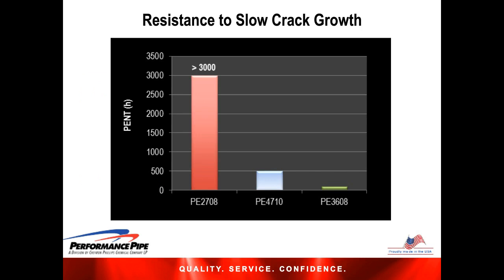For resistance to slow crack growth, a PE 4710 material requires greater than 500 hours of PENT testing, compared to the previous PE 3608 material requiring only 100 hours of PENT testing, while the new PE 2708 material achieves greater than 3,000 hours of PENT testing. This virtually eliminates slow crack growth as a failure mode.